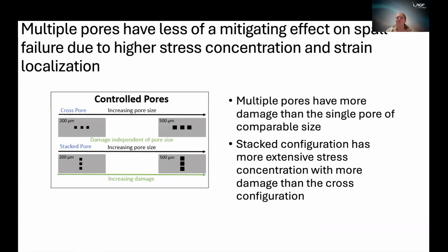So overall, multiple pores have more damage than the single pore of a comparable size for the large configuration, and the stacked configuration has more extensive stress concentration with more damage than the cross configuration. So when you start to add more pores, a smaller size seems to be more effective at limiting the damage, but it does depend on your configuration. Stacked pores, so multiple pores in the direction of impact, has more damage than we see for the cross configuration.